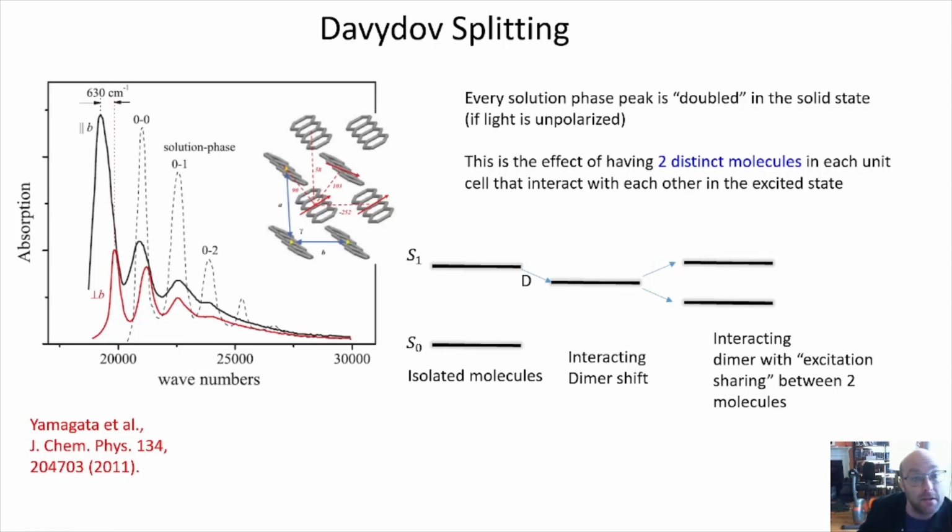And that's going to lead us next time into thinking about how these Frenkel excitons are mostly localized on a molecule, but not perfectly, right? There's always going to be some leakage in a solid. And again, it's a specific solid-state effect that only occurs for crystal structures where there are 2 molecules per unit cell, and that's not every crystal structure. You'll always have some shift due to the fact that an isolated molecule is now in a different environment than it was in, say, the gas phase or the solution phase. Whether you get Davydov splitting is highly dependent on the type of crystal that you form.